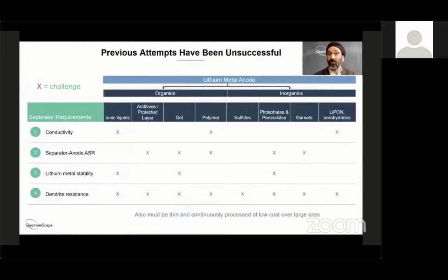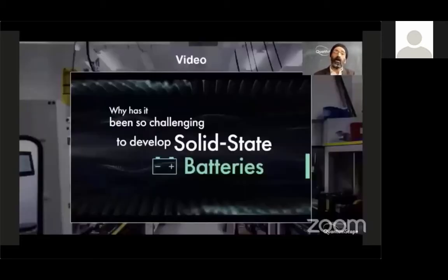It has to be natively stable to lithium metal, which is hard because lithium is very reactive, and it needs to prevent the formation of lithium metal dendrites. And it turns out on that last particular metric, none of the other materials that have been tried over the last 45 years have been successful. So people have looked at liquids and polymers and sulfides and oxides, and every single one of those approaches has turned out to be deficient on the dendrite resistant property when you drive current density to practical levels. So to illustrate some of these points, here's a short video that will discuss why it's been so challenging to develop solid-state batteries.